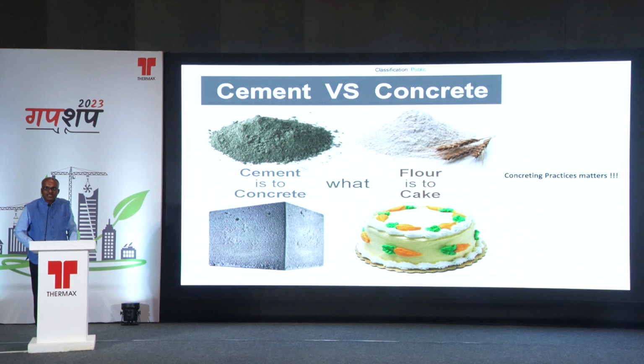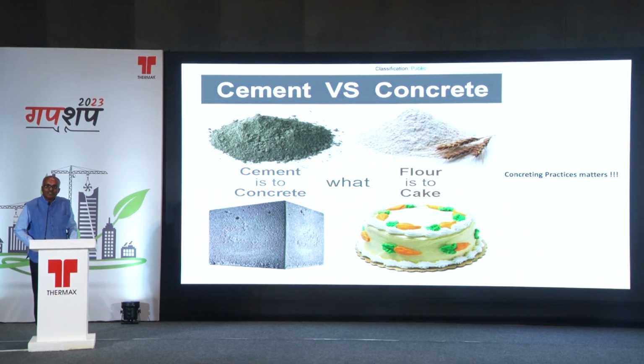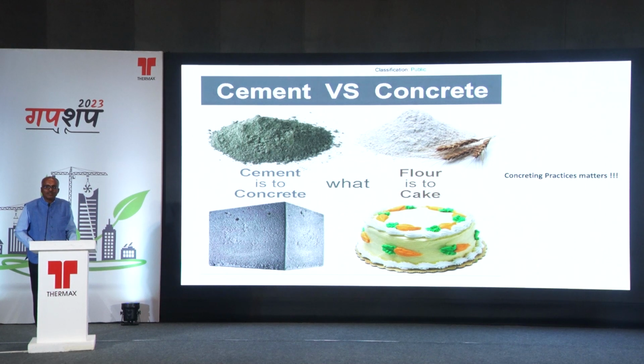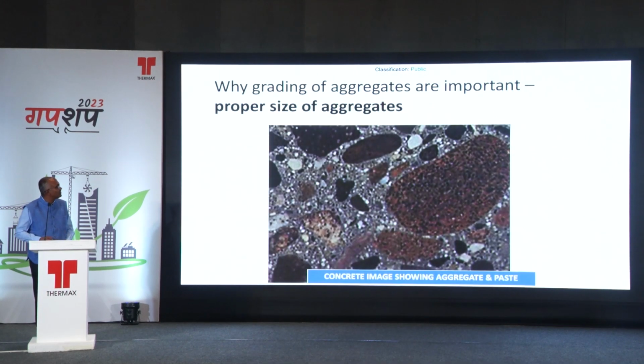What matters is concreting practices, because even after so many years, we will find a lot of small construction segments where they don't have sufficient infrastructure to measure the quality of concrete. For example, water cement ratio is one of the important things that we will find is being compromised. You will find that we rarely do the grading of aggregates because there is no choice in many places. You don't have those sieve analyses which we would have learnt in our professional courses. Rarely can it be followed. But as the grade of concrete goes higher, it is very critical that grading of aggregate has to be there.